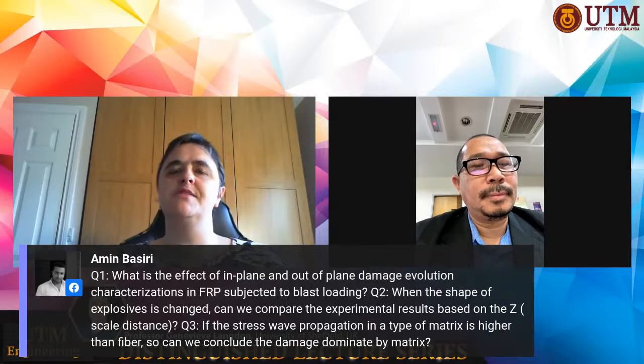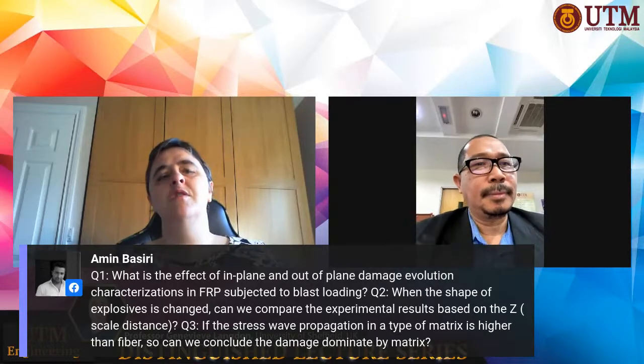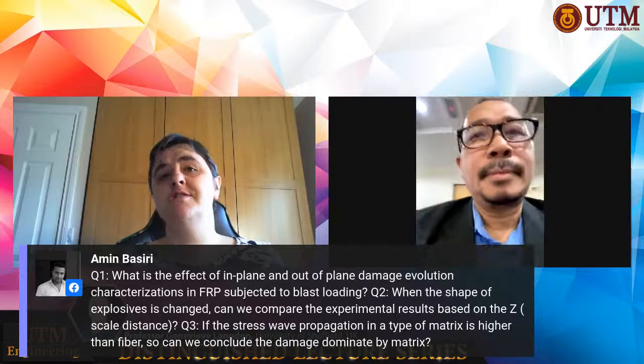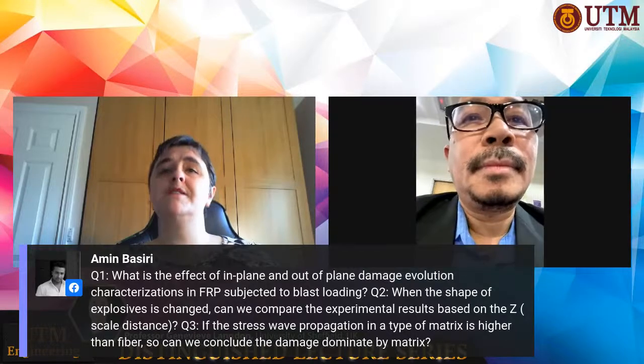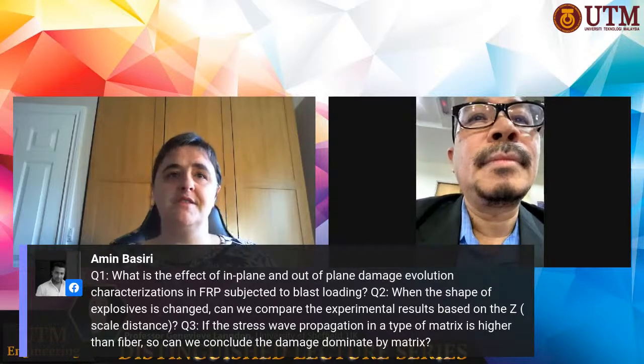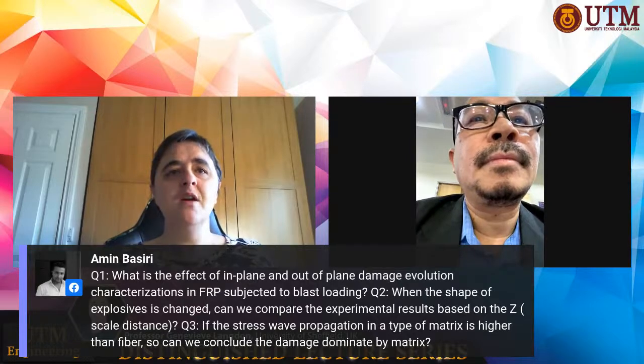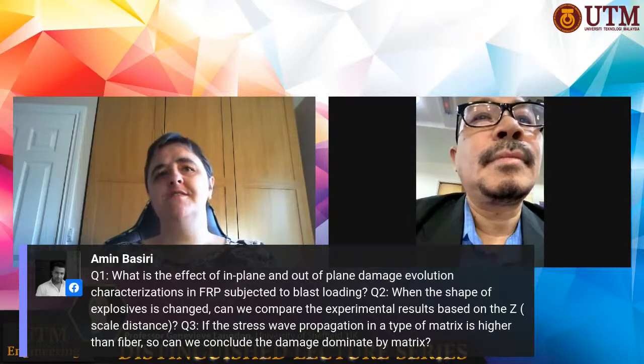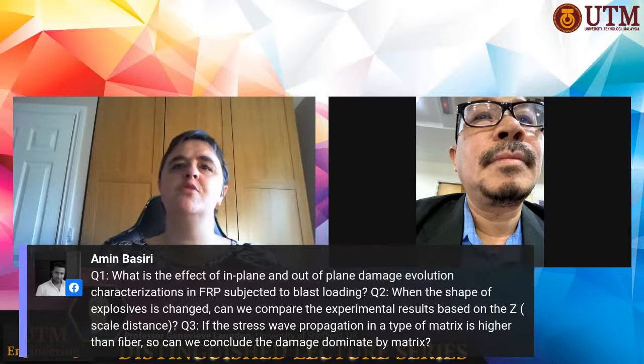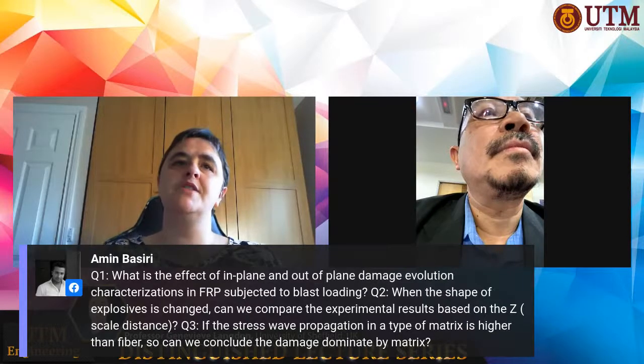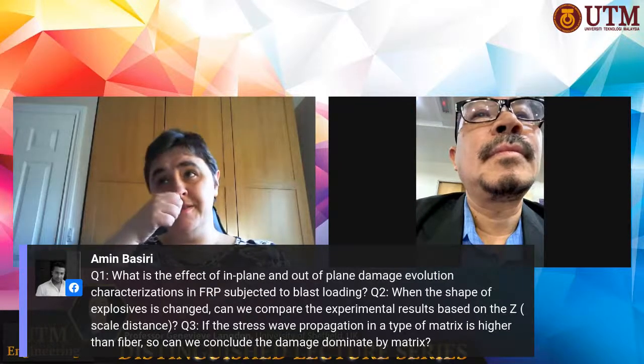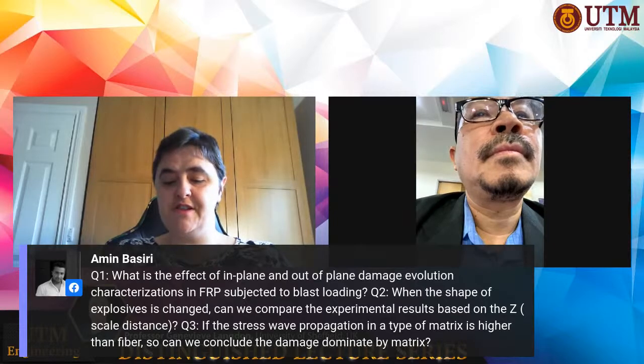If the stress wave propagation in a type of matrix is higher than the fiber, can we conclude the damage is dominated by the matrix? What you can conclude is that the stress waves will propagate more quickly in the matrix if that was indeed the case. But I have mostly seen the case where the stress waves propagate more quickly in the fibers than they do in the matrix.